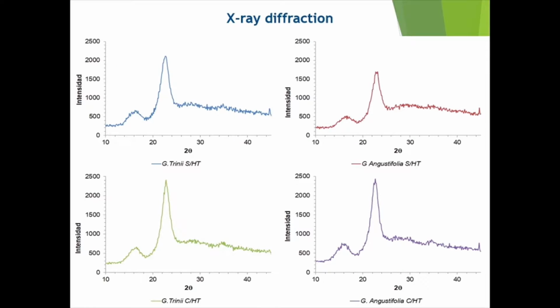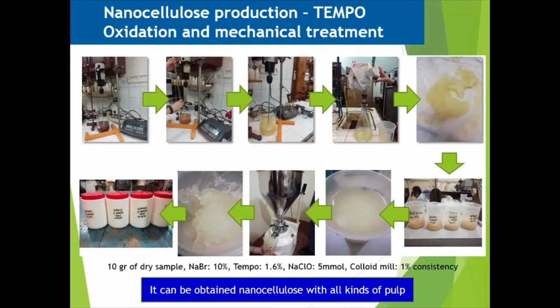In the graph, we observe the characteristic diffractograms for both species with and without hydrothermal pretreatment. These typically represent semi-crystalline materials, and the peaks are located in the same position in all species between 22 and 23 degrees. There are various methods to obtain nanocellulose.